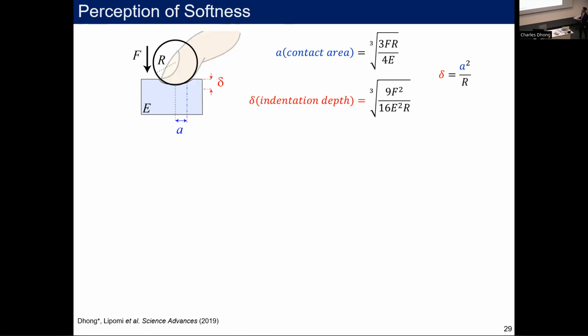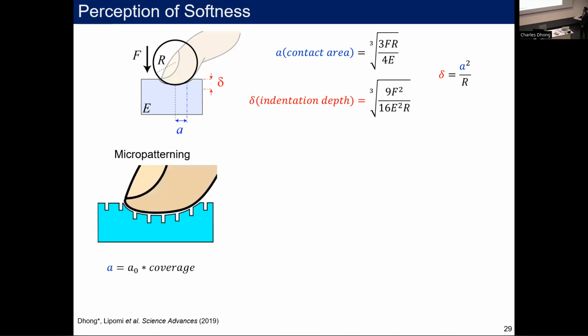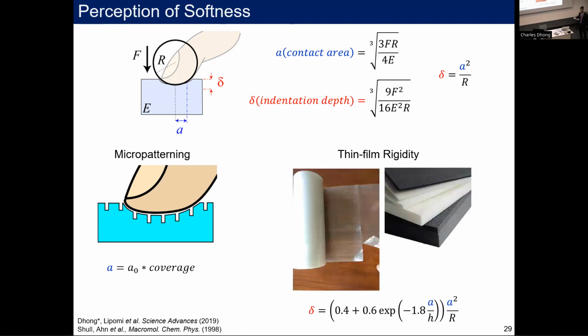And that's the big problem. And R is the finger, and people are using the same finger. So what we did is we did two ways to break this relationship. One is very simple, where we just have some micro patterning, right? If you can't touch the bottom, then that reduces the contact area. And of course, it has to be small enough and so on and so forth.